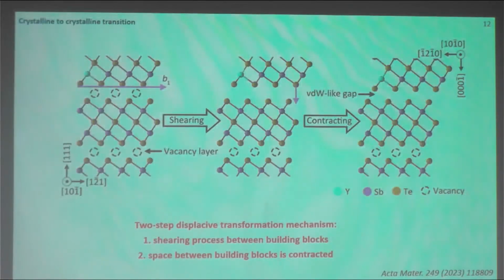This was also nicely confirmed before in our publication on the system antimony telluride, showing how this process occurs. In antimony telluride, we can also have two vacancy ordered phases. And if you use DFT calculations and try to shear these blocks, antimony telluride consists, as you know, of building blocks, quintuple layers, with a vacancy layer in between, and if you make the shearing of the blocks, then they can transform from one phase to another phase.